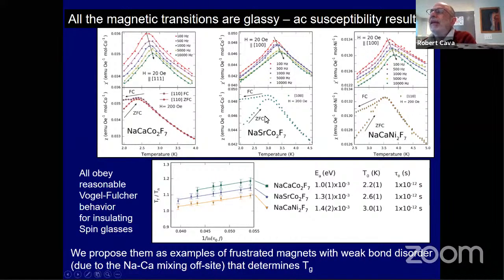And in fact, I think that the reason that these things order at all to make spin glasses is because of this random distribution of sodium and strontium or sodium and calcium on the neighboring sites. So they are spin glasses, but we think that you get the classical spin glass behavior, which you can trace with this kind of thing where you change the frequency of the magnetic field and then watch the relaxation rate change. And that's the classical case of a spin glass.